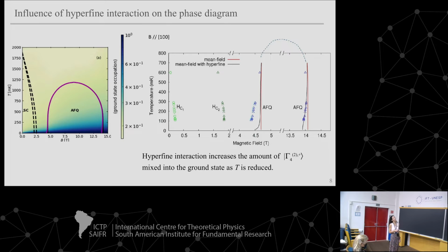So we put it into the mean field model, and I see now from this picture that it's a bit dark for you to see, but there's a black line which gives the phase boundary without the hyperfine interactions included. It's also over here. The red line is the regular mean field phase boundary. And the purple line here, same as the black line over here, is when we include the hyperfine term.